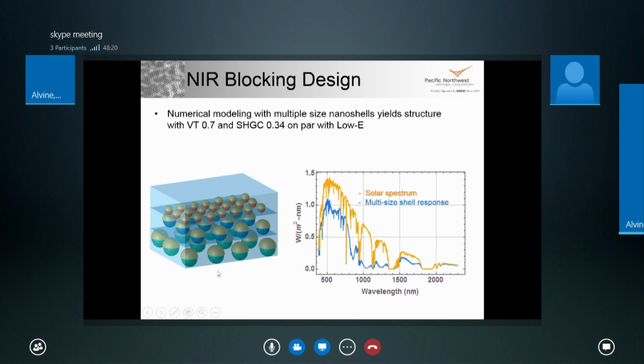So we can use these nanoshells to do this. Here's an example of 3 different nanoshells combined together and the effect on the solar spectrum. We can see we can effectively notch out the near-infrared signal to mitigate solar heat gain using those structures. So this is something that would behave like a low-E window, but would use significantly less metal and would also be amenable to things like daytime radiative cooling, because it doesn't block into the deep infrared if you don't need it to.